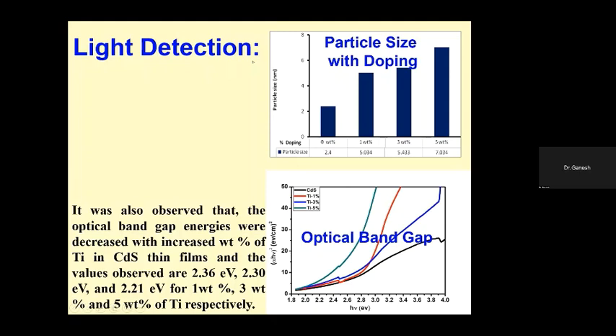Here the particle size during the synthesis, the particle size with doping concentration, is presented. So for 0 weight percent, we have a particle size of 2.4 nanometers. For 1 weight percent, it is 5 nanometers. At 3 weight percent, it is 5.4, and at 5 weight percent it is 7.03 nanometers. So the particle size depends upon the doping concentration.